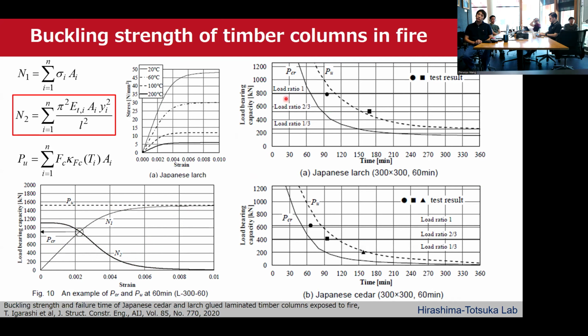The load-bearing capacity of the column obtained from the load-bearing fire tests was found to be between the compressive strength and the buckling strength of columns exposed to higher heating, including the cooling down phase. However, it's unclear whether the condition when cooled inside the furnace is the same as the condition during an actual fire.